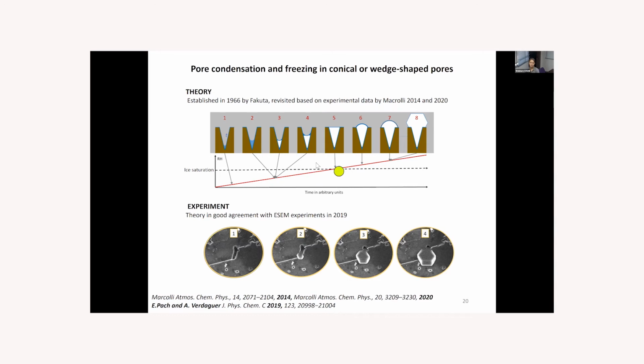And as you can see here, this is a schematic of the pore condensation and freezing in conical and wedge-shaped pores. Here you have a curve of relative humidity. At low relative humidities, the pores are wettable. They have a thin layer of water on them, and they are filled with a little amount of water. When the relative humidity increases, the amount of water in the pore increases, but the water won't freeze until we get the volume which is required for the critical nuclei to form.